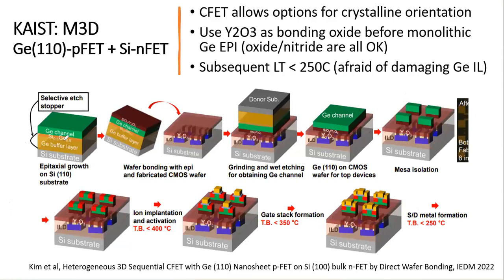And KAIST did it differently. They put SiO2 and then yttrium oxide together. Yttrium oxide is a very tough material, very good, very high k as well, and has many unique properties. They decided to put the device on top, and then they flip it, and then they start to put devices on the germanium layer. This flow is quite straightforward.